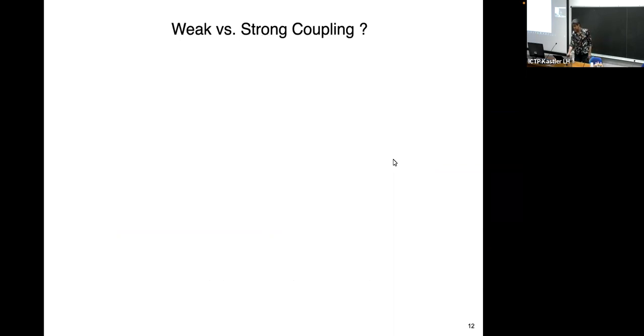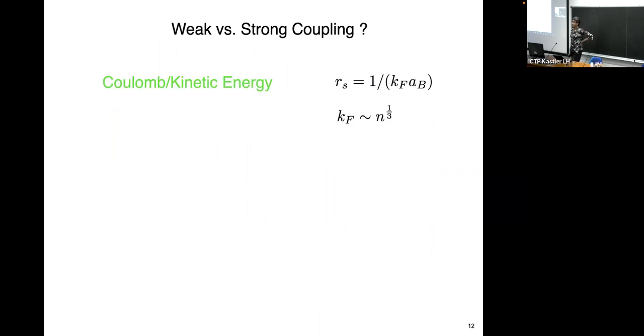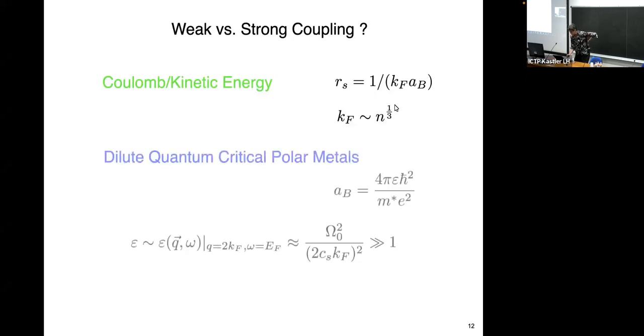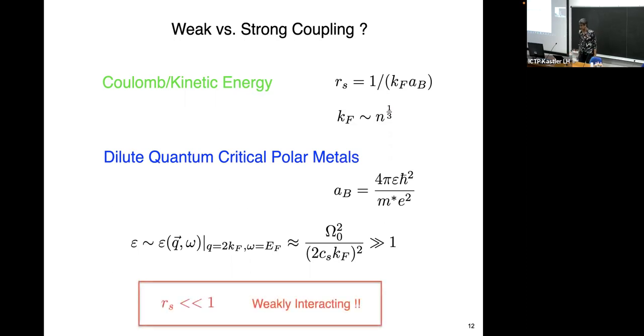Now, to answer Colio's question, weak versus strong coupling. Normally, when we have a very dilute system, we have strong coupling. So when we look at weak versus strong coupling, we compare the Coulomb to the kinetic energy. RS is then 1 over KF a_B. And since KF goes as n to the 1/3, you might think that this might be very large. But as has been emphasized by Dmitry Maslov, what's interesting about dilute quantum critical metals is that the Bohr radius includes the dielectric constant, so it's quite large, and RS is very, very small. RS is much, much less than one, and so we're weakly interacting. That's because we're close to the quantum critical point.